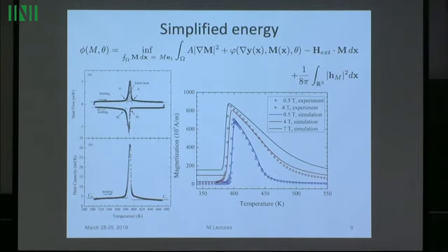And the other extremely important thing in this energy conversion, which I already mentioned and which was already in this experiment with this very large field, is the fact that the phase transformation temperature can be changed by bathing the specimen in a magnetic field. There's an effect of the magnetic field on the transformation temperature, and that's extremely important here. Without that effect, you'll not generate electricity by this device. So this is both experiment and theory.